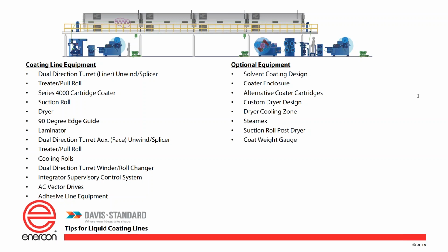Coming out of there, the last dryer, you can add a cooling zone if it's an adhesive coated web. You can add a Steamex. A Steamex is a unit that applies moisture back to a web. So when you're drying, let's say, a silicone-coated piece of paper at an elevated temperature, the paper goes in the oven generally at 6% moisture. When it comes out, it's going to be reduced. And you want around 6% to be stable. What's sitting on the table in front of you is usually around 6% on your notepads. So you apply the moisture back in.